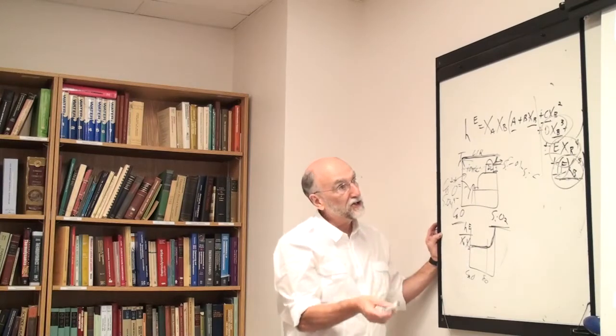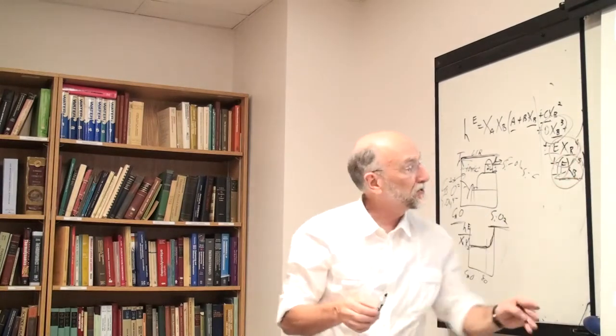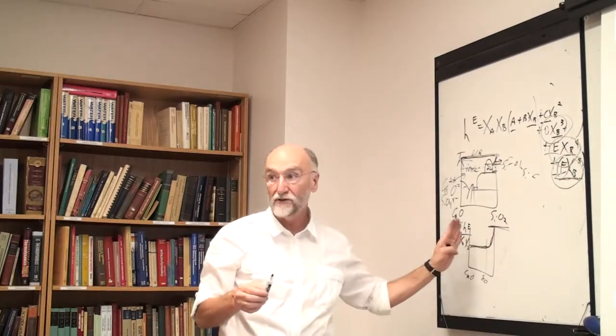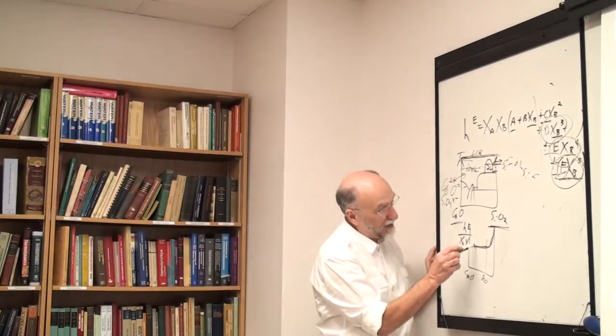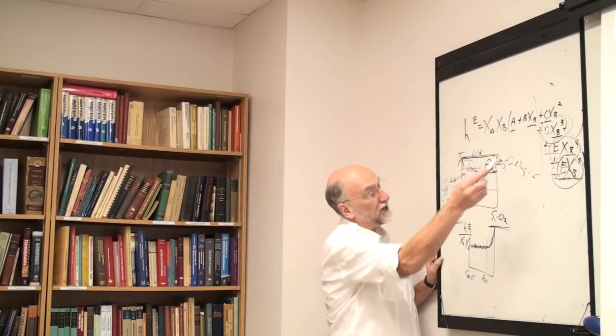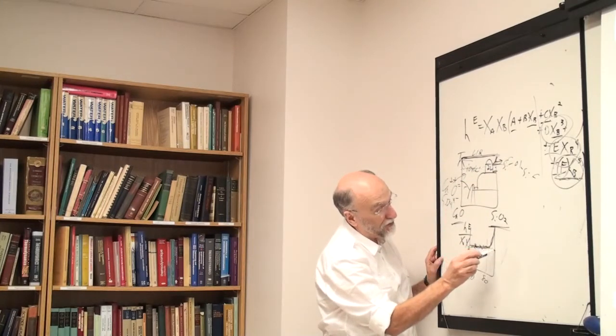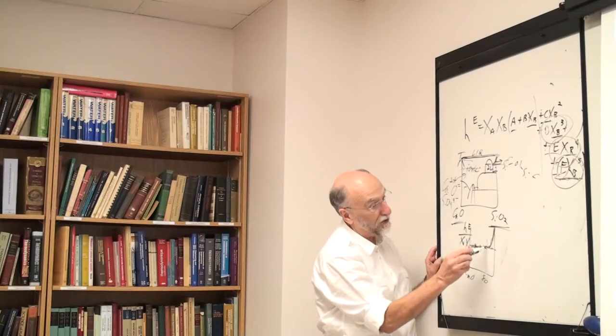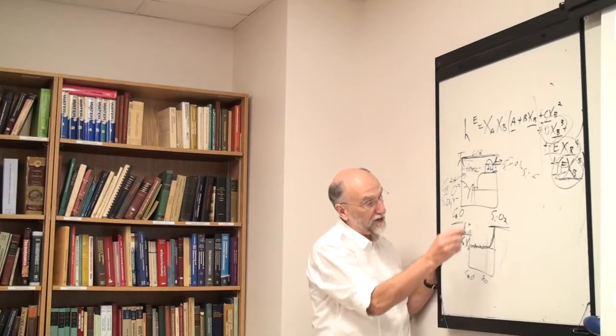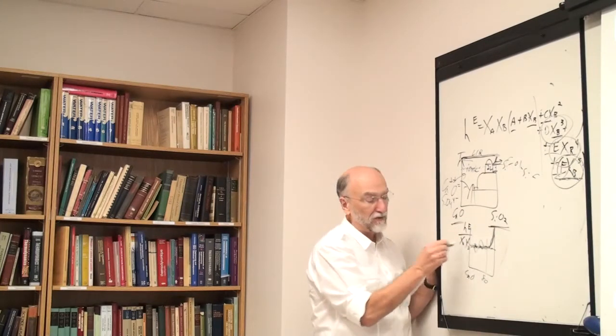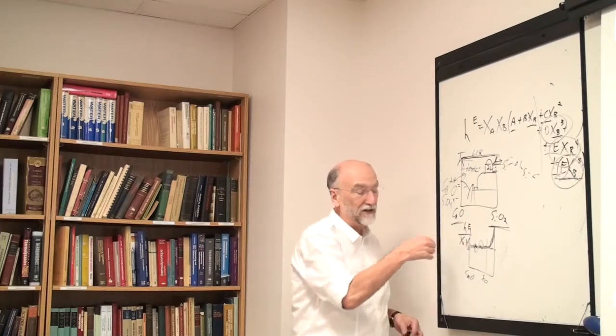If you start to use the Redlich-Kister, though, every term in the Redlich-Kister expansion basically has an effect over the whole composition range. So now I use one or two terms. I use, say, two terms, I get a nice fit here, but of course it's no good over here, so I start to add more terms in order to get this thing going up at the end, and now I find it starts to mess things up over here again. And I have a hell of a time trying to fit the thing.